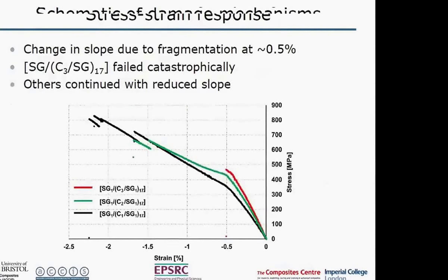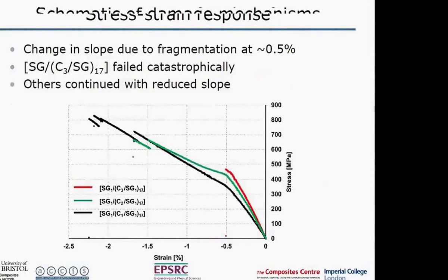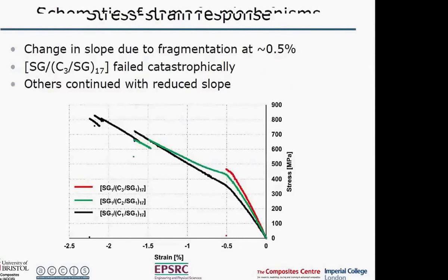We see a changing slope at 0.5% strain, as we saw in the bending case, and a different response depending on the thickness of the carbon. When we have 3 carbons blocked together, catastrophic failure occurs shortly after fragmentation starts at about 0.5% strain. When we have thinner blocks of 2 or 1 carbon plies, we see a change in slope, it goes up to a higher strain, and then we get a catastrophic failure at a later point.